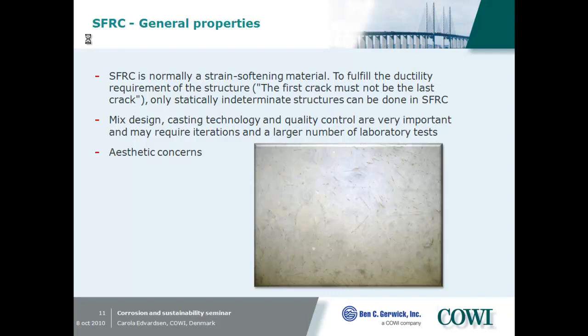I can tell you that the type of aggregate has a tremendous influence on the tensile capacity of steel fiber reinforced concrete. For steel fiber reinforced concrete, it's the tensile capacity and not the compressive strength which is the decisive structural parameter. We design according to the tensile capacity. The type of aggregate has much more influence on the tensile capacity than on the compressive strength. We used in Denmark a concrete mix which had been very well used in Germany for steel fiber reinforced concrete. The only difference was that we used Danish aggregate compared to German aggregate.